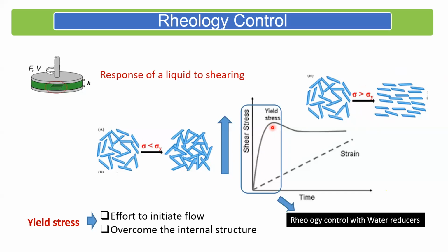And this is key to understanding that when I have something like cement paste, which is a very dense particulate suspension, these materials don't flow immediately, even if you apply shear stress to it. And this is key in understanding. The yield stress that we measure from this rheology ties with the slump that we measure, because when I lift the slump, the cement paste does not immediately want to flow, and it tries to hold on to its shape. And eventually, when the gravity-induced stress in the slump cone increases beyond what it can sustain as the yield stress, then it starts moving. And that's why we get this slump measured in the concrete.